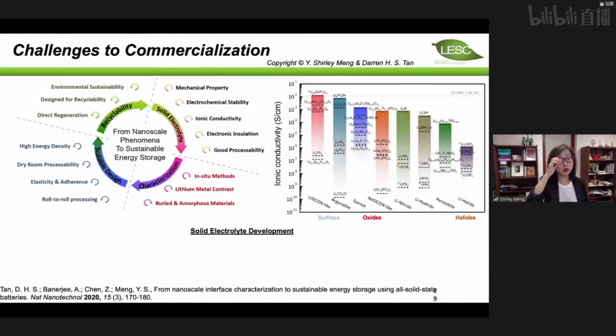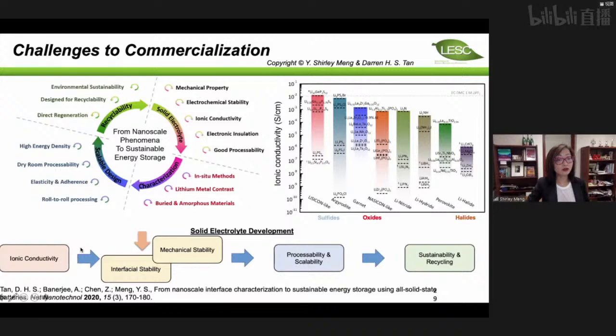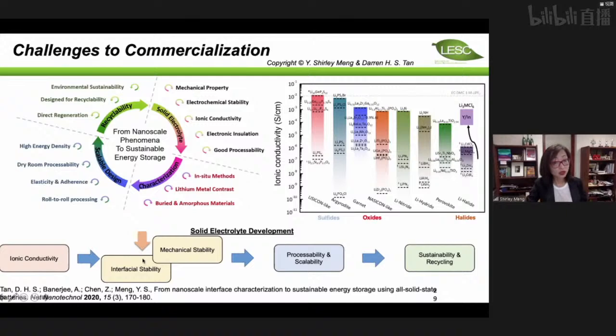So if I have to give a quick summary of what happened in the solid-state battery field, I believe in terms of ionic conductivity, we have plenty of candidates: sulfides, oxides, halides. Just 2 years ago, the halides reported record-high conductivity numbers. Now, our challenge of interfacial stability is being well addressed because we developed quite a lot of advanced characterization methods. In terms of mechanical stability, I will put a question mark here. And more importantly, because we are switching from liquid electrolyte to solid, how the processability and scalability look is still a big question mark, right?